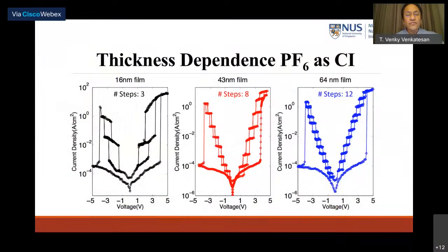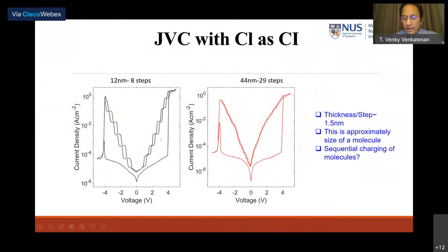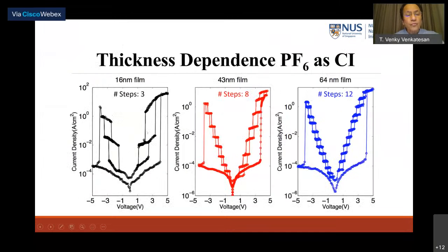Okay, this is very remarkable. We essentially work in a certain range of these devices, and it shows multiple hysteresis loops. And what is really happening? This is a 16 nanometer film, and if you look at it, there are basically 3 separate hysteresis loops here. If I take 16 divided by 3, I get a number which is approximately 5 nanometers, plus or minus something.